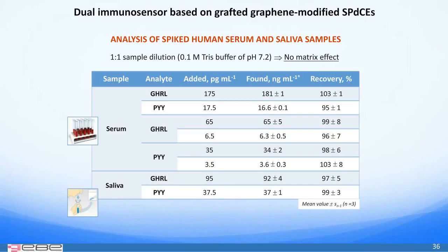Results achieved demonstrated that the accurate determination of both hormones could be performed simply by interpolation of the electrochemical signal obtained for sample diluted 1-1 into the respective calibration plot constructed with a standard solution. These results confirm the suitability of the approach for the analysis of these complex samples after minimal sample treatment.